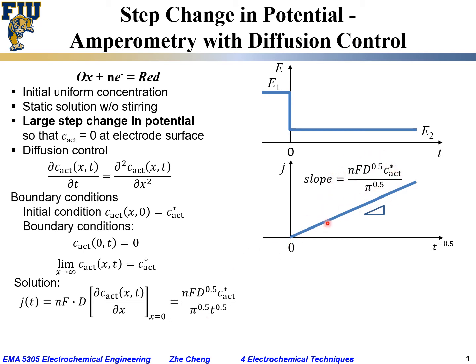Okay, and this slope relationship can be used to measure the diffusion coefficient if you know the initial concentration, or if you know the diffusion coefficient you can determine the initial concentration. This equation between current density and the square root of time t is called the Cottrell equation, and quite often people use it to measure a series of current versus time and then plot current versus the inverse of time to the power of 0.5, and the slope would give us either the diffusion coefficient if we know the initial concentration, or the initial concentration if you know the diffusion coefficient.